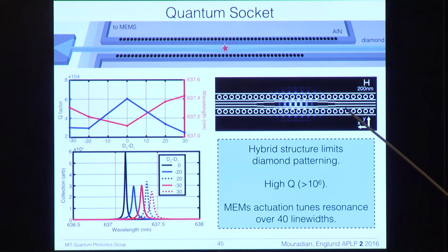And so we don't need intense fabrication in this diamond in the center here. But luckily, diamond has a high index of refraction, which pulls the mode into the diamond. So when we increase the diamond width slightly at the center, we get this localized mode in the diamond at the center of this cavity. And so with this, we can get very high Q cavities, larger than 1 million. This structure limits the patterning needed in the diamond. And also we can use the MEMS in aluminum nitride to tune the resonance.